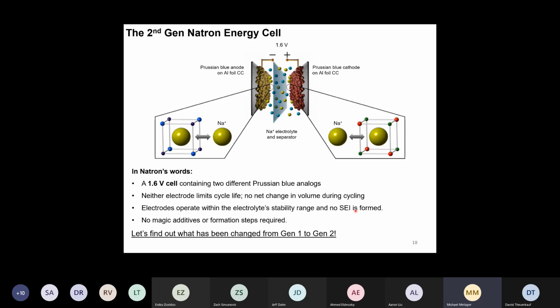So, in a lithium-ion battery, as we heard in the electrolytes class, the graphite is actually operating below the stability limit of the carbonate electrolytes, right? And luckily, we form this passivating SEI layer that prevents further electrolyte reduction. But in Natron's case, this is not even needed because you operate fully within the stability limit of the electrolyte. And that's, of course, better because you don't have impedance build-up in these cells from a passivating layer on the surface. And then they say no magic additives are in these cells.